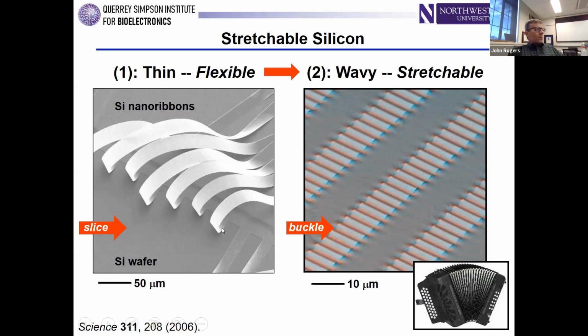And the way to get to stretchable is you take these thin ribbons and then you bond them to an underlying low modulus elastomeric substrate, such as a silicone-based polymer, but you bond them not in a flat geometry, in sort of a wavy shape. And with that kind of buckled geometry, you essentially embody the physics of an accordion bellows in the sense that you can stretch and twist and deform this kind of hard, soft material structure in a way that allows large end-to-end level deformations with elastic restoring forces associated with the substrate, but in a way that doesn't induce fracture, without creating strains in the silicon itself, because these buckled geometries can change to accommodate the overall system level strain through changes in amplitude and wavelength. So that's pretty much it.